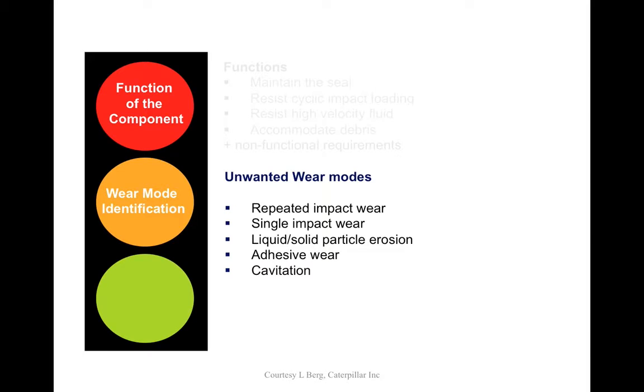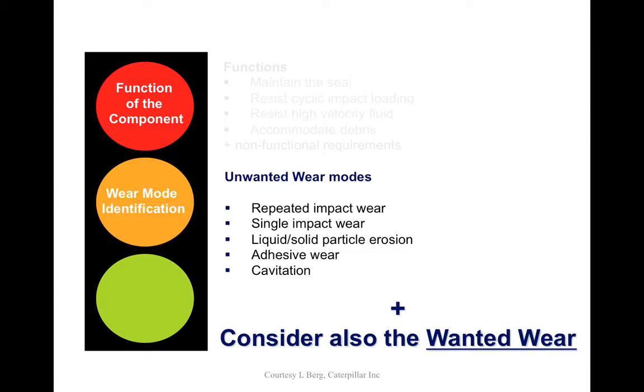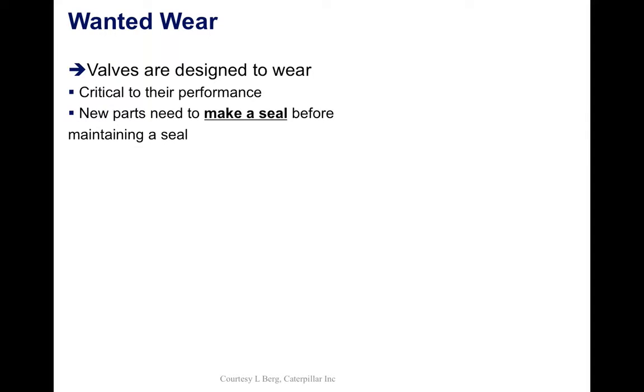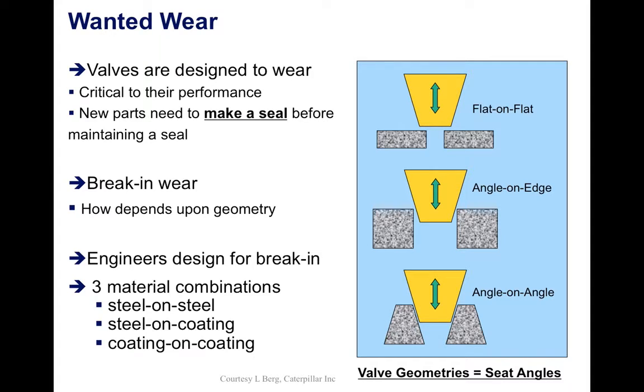So they've got their unwanted wear modes, repeated impact, single impact, erosion, adhesive wear, and cavitation. That's great. We've identified the wear mechanisms. We've seen some coatings that work. However, they also want wear. You didn't think that. Well, you wouldn't think that, but they do, because this coating has got to bed in to create the seal. So it's extremely challenging and demanding. So the valves should be designed to wear. They're critical to the performance. New parts need to make a seal before maintaining a seal. They need break-in wear under any geometry.